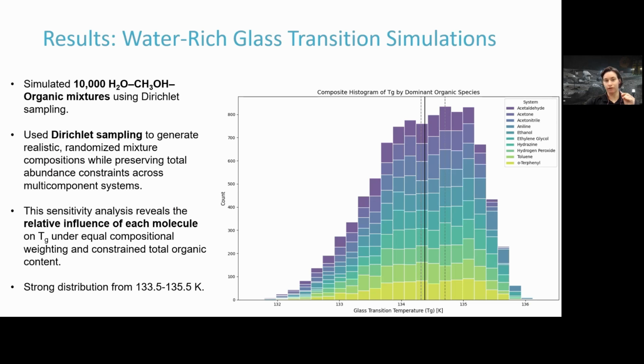The long and short of it is that for realistic cometary compositions of water, methanol, and some very small organic component, it basically converges to a distribution around 133 to 135.5 Kelvin. And that was over about 10,000 different samplings using Dirichlet to constrain the overall composition. Next slide, please.